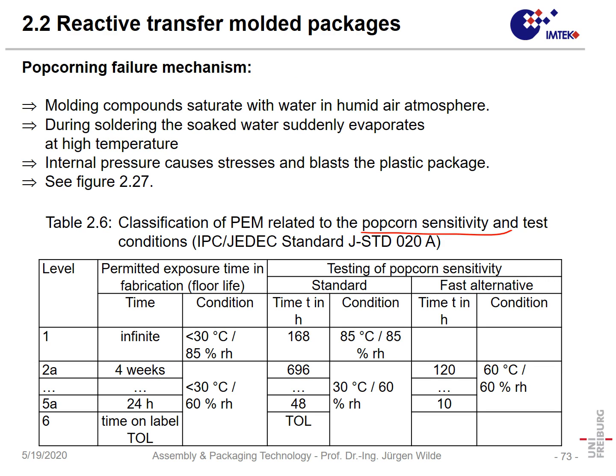Of course, when you produce packages, you want to have an accelerated testing, and that accelerated testing would mean, for instance, you make the test time shorter by increasing the temperature. For instance, for level 1, you go from 30 to 85 degrees centigrade. The humidity is maintained, and you keep this for 168 hours. And if after that, in a soldering process, this whole procedure is survived, you get level 1, or you have a non-accelerated test for the lower popcorning grades,